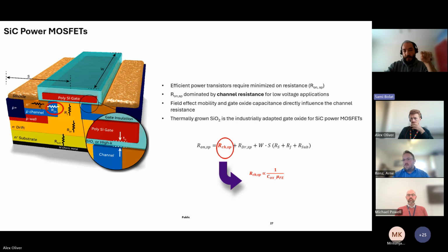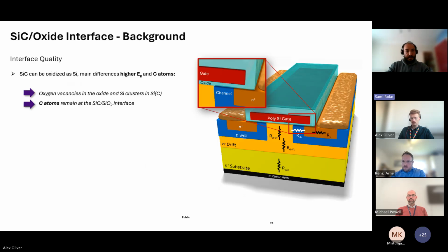And in today's world, we have the thermally grown silicon dioxide as the industrially adopted gate oxide for the silicon carbide power MOSFETs. So if you take a look at the channel resistance in this formula, we can see that the oxide capacitance and the field effect mobility are inversely related to the channel resistance that we get in a device. And this field effect mobility is directly related to the interface between the dielectric and the semiconductor. In the next slide, I will touch upon this a bit.